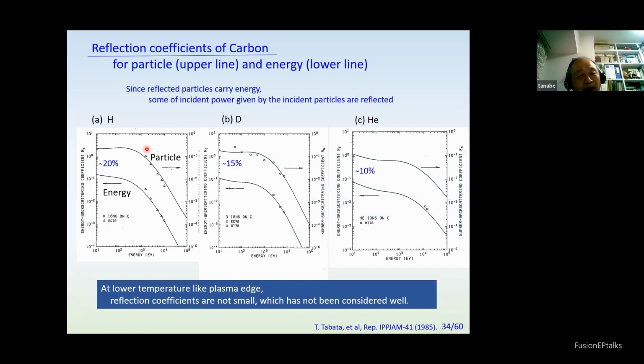In re-emissions, reflected particles are included. I thought this reflection is quite important because the reflection coefficient is not so small at low energy. This is particle reflection, and this is energy—because the particle carries the energy, reflection of particle and energy are quite similar, though shifted one order of magnitude to show this.